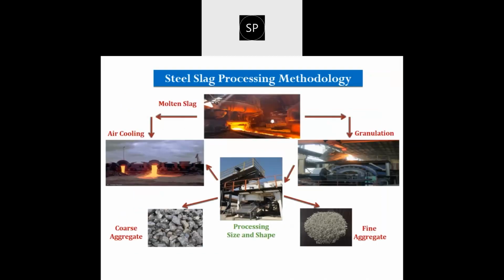Now here is a glimpse of the entire process which is carried out inside the steel plant. In the first photo you can see the molten slag is coming out from the furnace. It is tapped from the bottom. Later on it is transported to the slag pit, where the air cooling is carried out. Once it is air cooled, then magnetic separation and crushing may be required to be carried out as per the type of slag generated in the slag pit, and subsequently it can get converted in the form of a coarse aggregate.